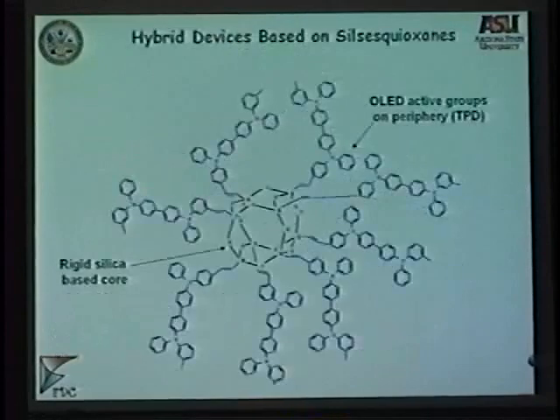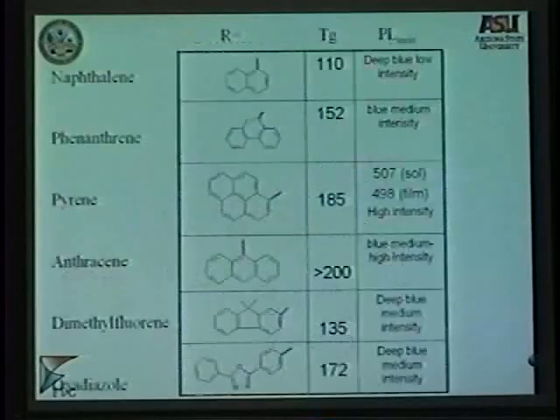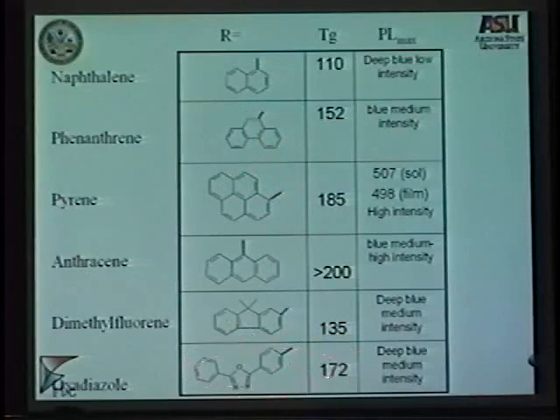understand. And this is TPD, triphenyldiamine, is very low TG material, about 60 degrees C. And when you put it on this cube, it becomes more than 100 degrees C, as I will show you on this table. We have taken all these materials. Some are used for solar cells, some are used in our labs for OTFT, and some are for organic LEDs. And you can see the oxadiazole, which has a TG normally lower than 40 degrees C if it is in its very pure form. It moves up to 172 degrees C.